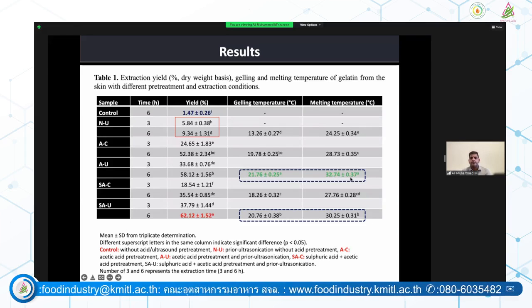So this is good, suitable for preparation of various food products, gelling products, as well as packaging material, mainly edible packaging. And we saw that with sulfuric acid the extraction yield was higher, but the gelling property was a little bit lower when compared to acetic acid. So we found acetic acid has good potential for gelling and melting properties,